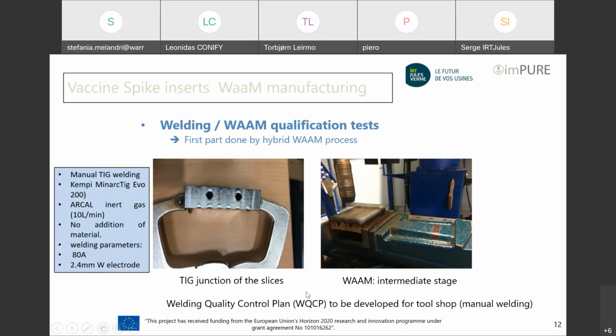And when the TIG junction of the slices was completed, we performed the WAAM. Here, the 10 millimeter WAAM by 3 layers. And here you see we have just the full deposition. We have 5 layers. And at the end, to reduce the extension collapse, we add a transverse deposition.